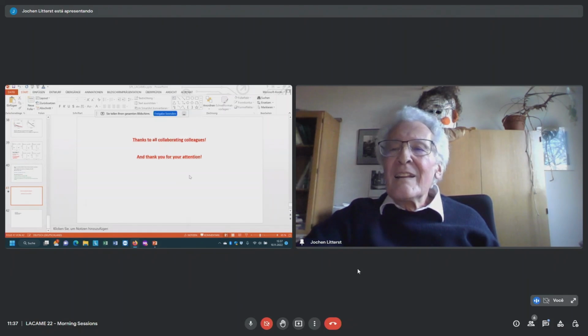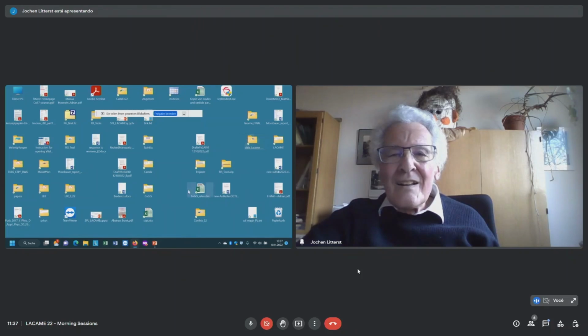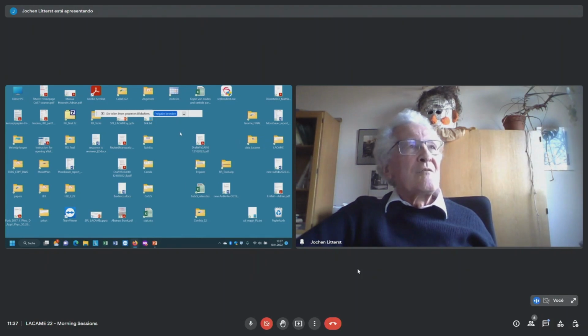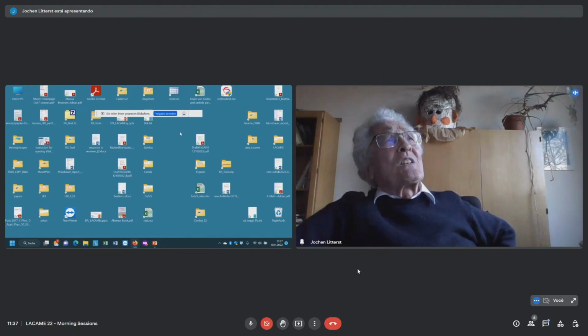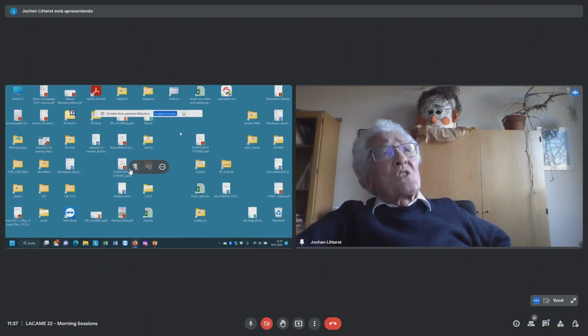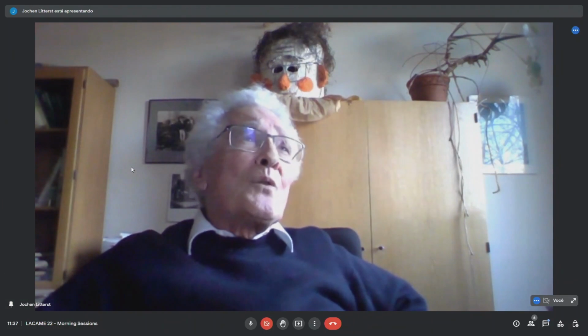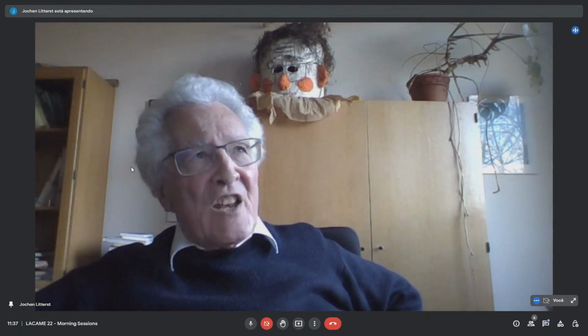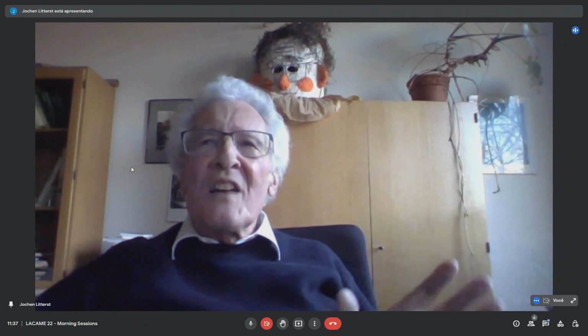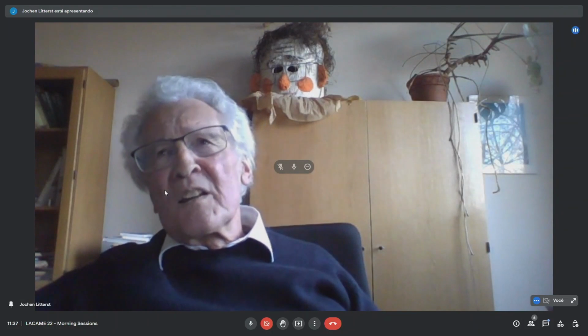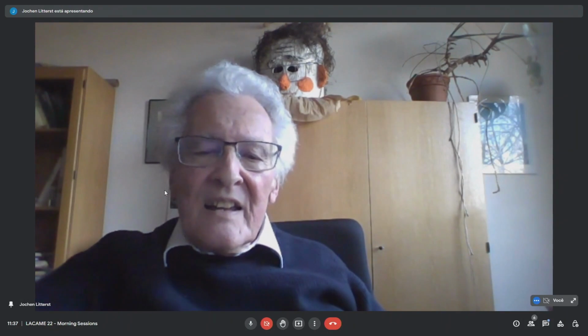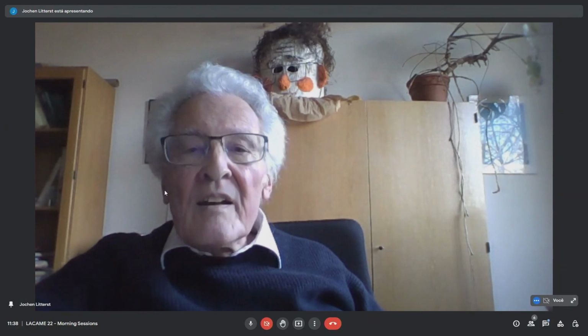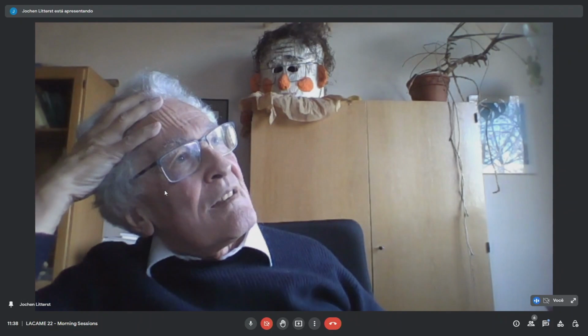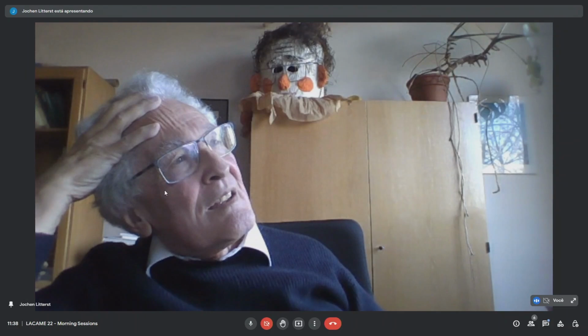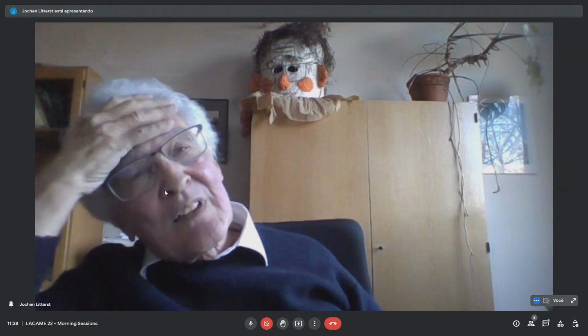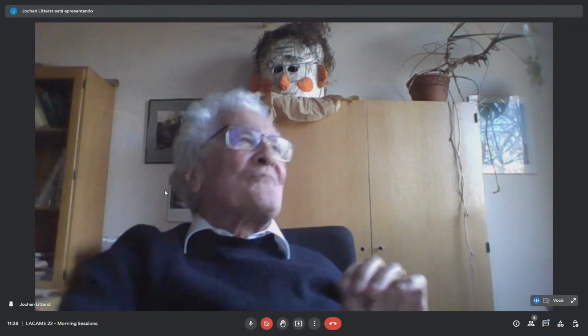I don't know if it's a silly question, but when you talked about this iron scandium sulfide, you say that it is close to a quantum critical point, right? Yeah. So, the competition is between an extreme strength of spin orbit coupling on one side, and on the other side, the antiferromagnetic exchange. And if both come close in strength together, then you will have a quantum critical point. That's predicted from theory. Okay, so my question was if you can extract the signature of the quantum critical behavior from Mössbauer spectroscopy, or from muSR, I think that is much more plausible. But from Mössbauer spectroscopy, I don't remember having seen any work showing a signature of quantum criticality. Maybe you can answer that for me.